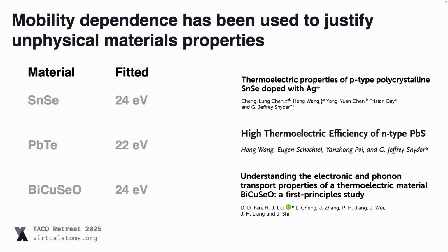And just lastly, why do we think this is important? Well, the temperature dependence of mobility has really been used to justify ascribing the factors limiting mobility to a certain scattering mechanism. And when you do that, you then start making assumptions about how you optimize your device. So if you're limited by polar optical phonons, the way you might optimize your device is different compared to deformation potential scattering. And so you can really get a very incorrect picture about materials optimization.